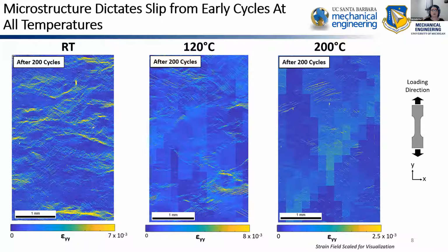That actually isn't the value of strain. There is very, very little strain occurring, and I could also have shown this in the shear direction or component. The big thing here is that it acts like there's a big strain, or this large strain, this bright yellow region, because there is a discontinuity.